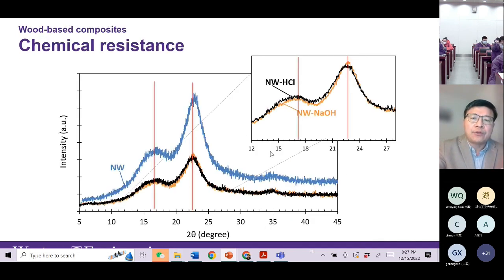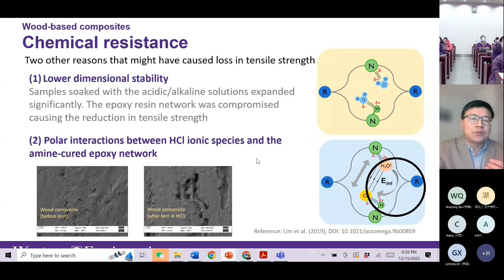We show that after we do the HCl and sodium hydroxide treatment, if you look here, compared to original natural wood, the crystallinity reduces. That's probably one reason. They become more amorphous, so they lose crystallinity. This could be one reason contributing to the strength reduction. In addition to the crystallinity, we also try to explain the mechanisms better.